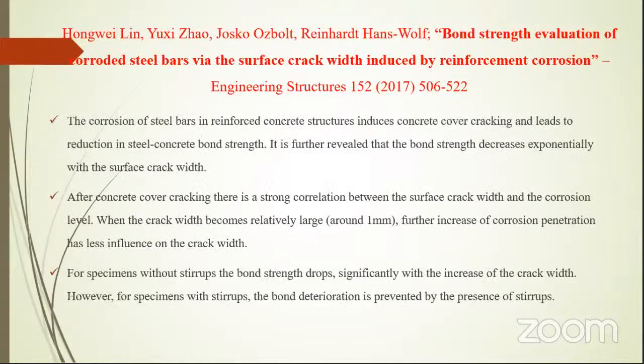The next literature is about bond strength evaluation of corroded steel bars via the surface crack width induced by reinforcement corrosion. The corrosion of steel bars in reinforced concrete structures induces concrete cover cracking and leads to reduction in the steel-concrete bond strength. It is further revealed that the bond strength decreases exponentially with the surface crack width. After concrete cover cracking, there is a strong correlation between the surface crack width and the corrosion level.